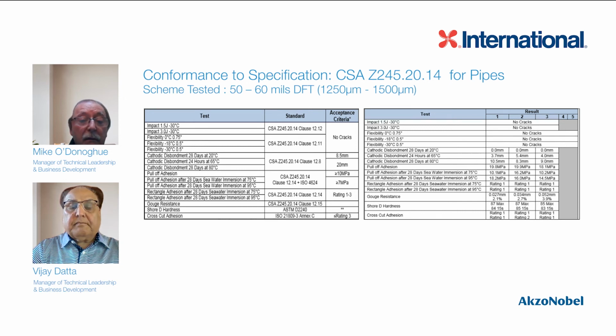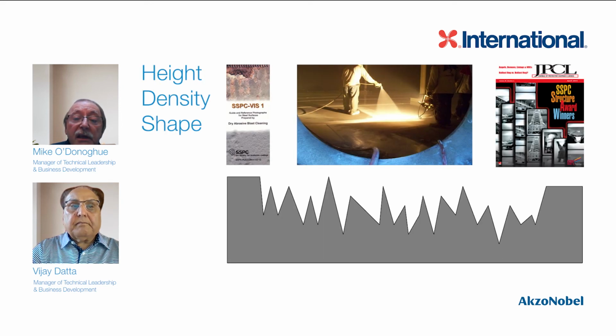We'll find there's no cracking and no defects. And the CD results, we've just mentioned those a few moments ago. Now, in order to get really good results from what we do, it's great to have a good coating like 376, but we've also got to make sure that the contractor applies it beautifully, properly. The surface preparation, obviously, is key here. And talking of keys, we want an angular profile, as you've seen in this particular slide.